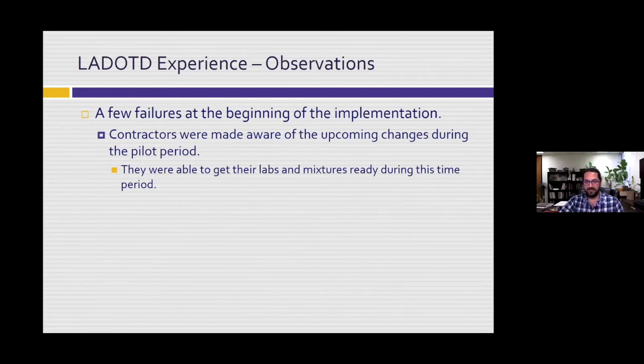There were a few failures at the beginning of implementation, of course, but most of those were just simply tweaks to the mixture design. They're not complete overhauls in terms of everything in the mixture design. Sometimes it's a binder that's not compatible. Sometimes it's a little bit too much dust or fine aggregate in the mix. I'm sure Barry's going to touch on a lot of the mix characteristics that he was able to tweak in order to meet the criteria. But really, for the most part, once the contractors were made aware of the upcoming changes, they were able to get everything in order, get their ideas on paper, and start tweaking their mixtures prior to actually being held to the specification.